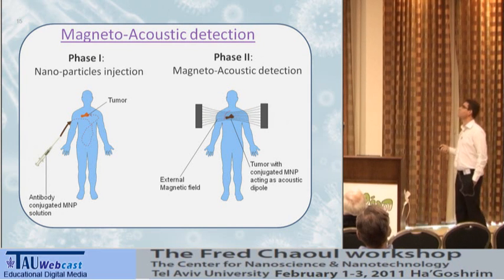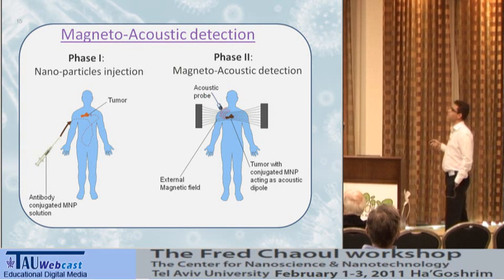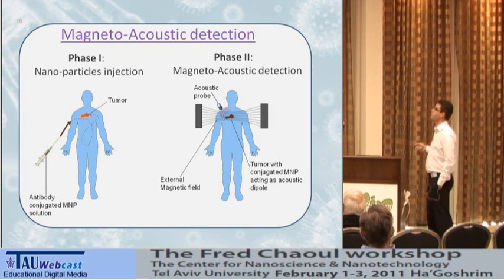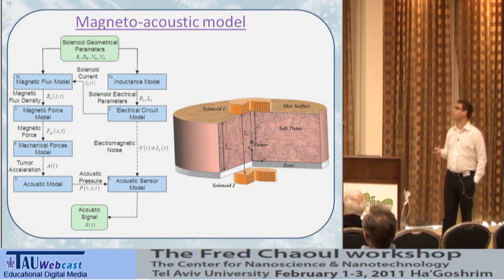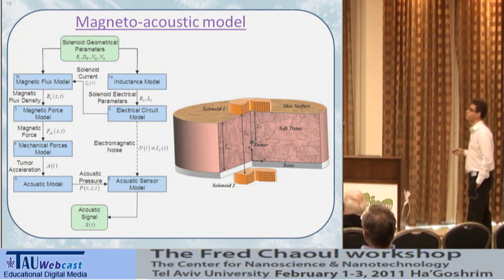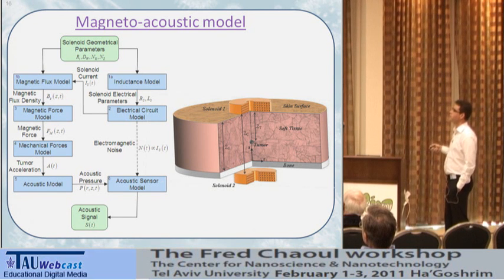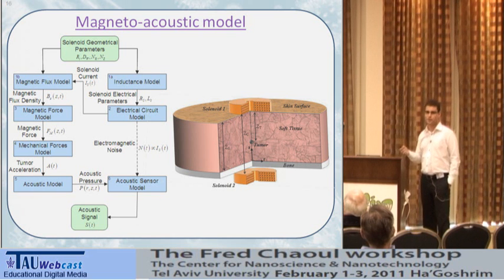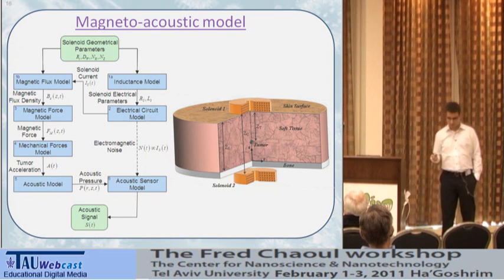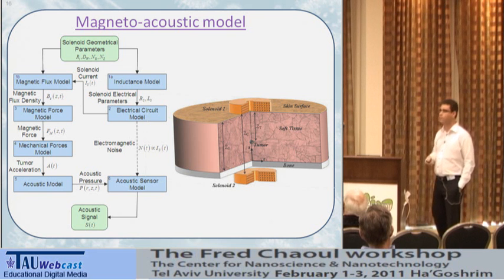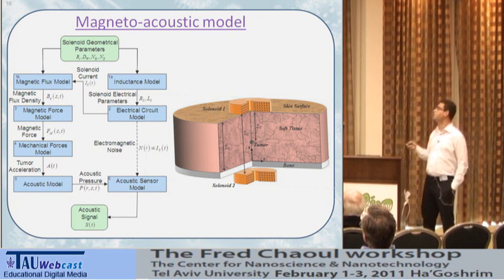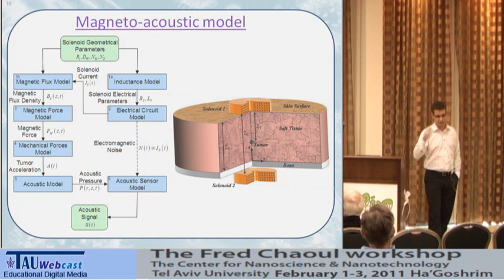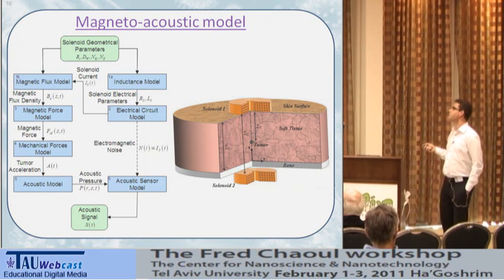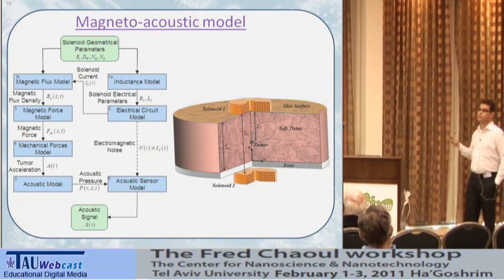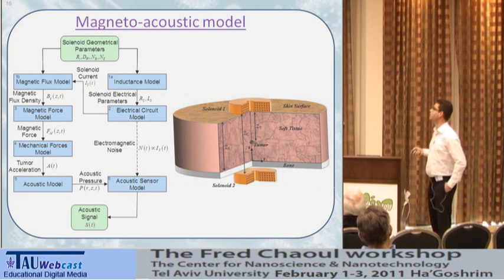An oscillating field gradient. And this will generate an acoustic dipole, which can be picked up by an acoustic probe. So again, we started modeling the entire scenario. We actually wrote 6 or 7 submodels, each designed to describe the different components of the system. There was an inductance model, which allows us to predict the inductance of various solenoids. There was a model for the driving electric circuit, which needs to drive these two solenoids, as you can see here, above and below the tissue.